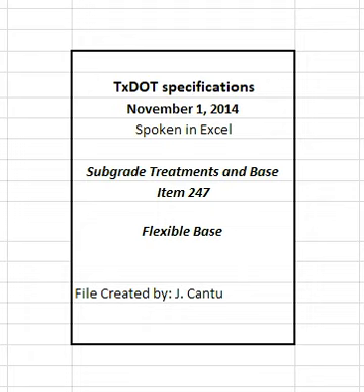Before final acceptance, the engineer will select the locations of tests and measure the flexible base depth in accordance with Tex-140-E. Correct areas deficient by more than 1/2 inches in thickness by scarifying, adding material as required, reshaping, recompacting, and refinishing at the contractor's expense.